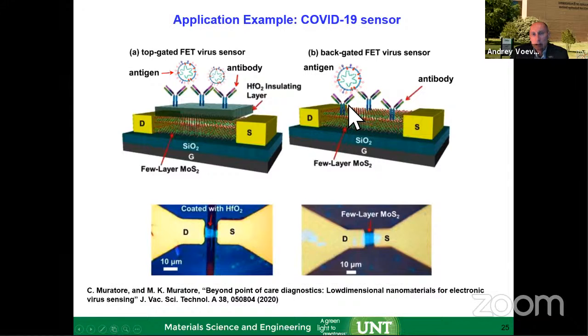So if you have these antigens attached to the sulfur, and that is quite possible because of the sulfur linkages reacting to that, then they're sitting there just waiting for when the virus will come around. And as soon as it comes, it connects here, and at this moment the charge transfer happens between the virus and the molybdenum disulfide, and this will affect the resistivity of that entire bridge, which instantaneously tells you, okay, I can detect the virus.